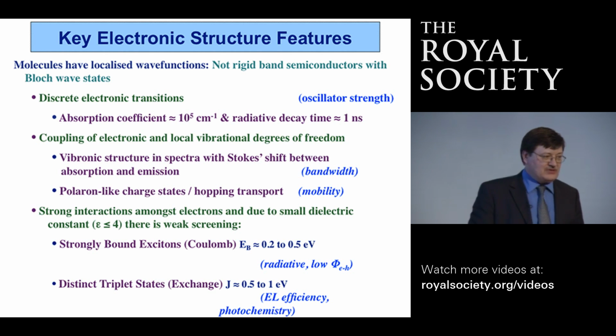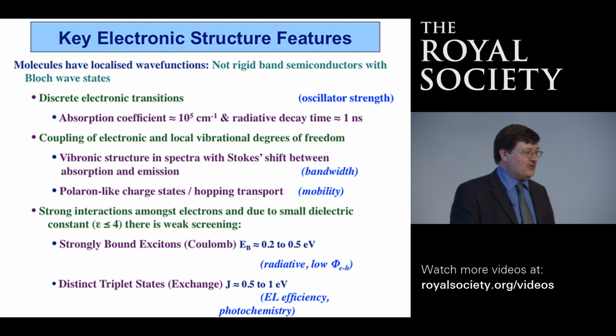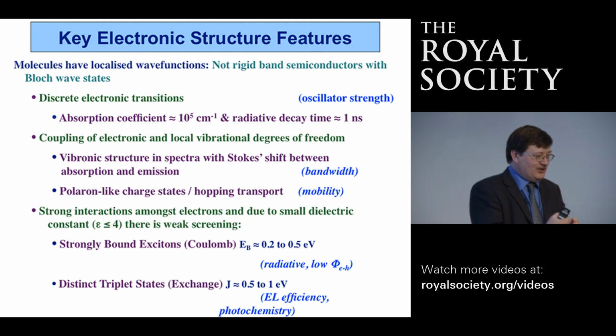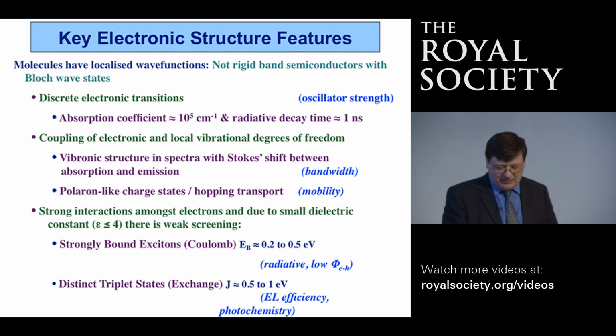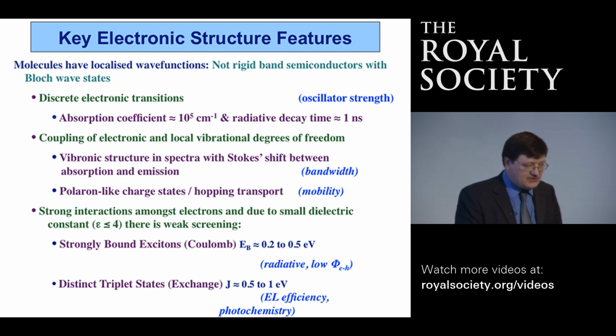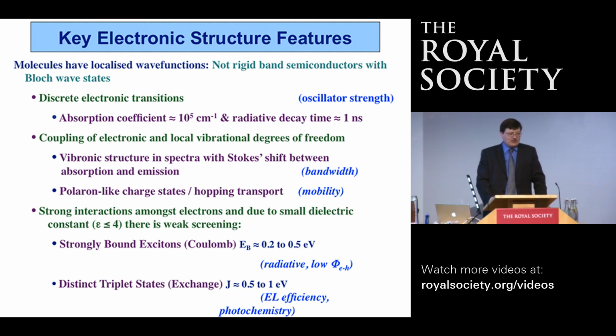And we end up with states which are strongly bound. So this electron and hole are strongly joined together. They're held together by a large Coulomb binding energy, which is about 0.2 to 0.5 electron volts. And we get other things from quantum mechanics. The fact that these states are described in terms of fermions means that we have triplet states. And probably not too much to say about that without going too far. So we can say that these are the key electronic structure features.